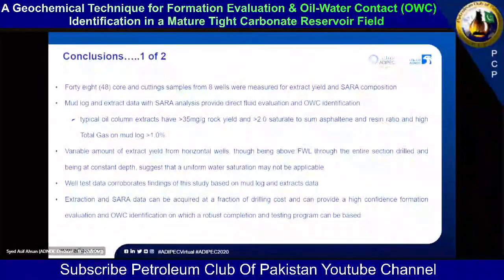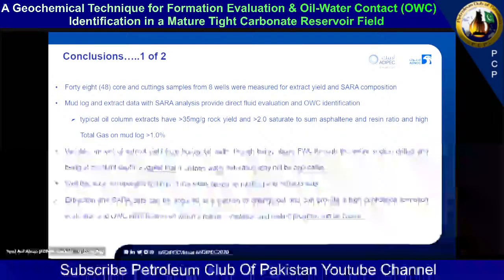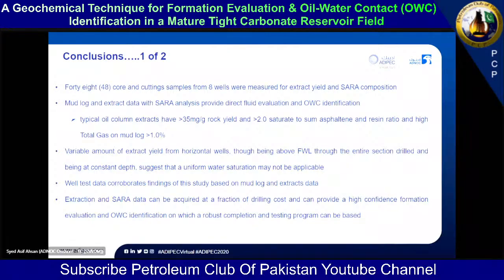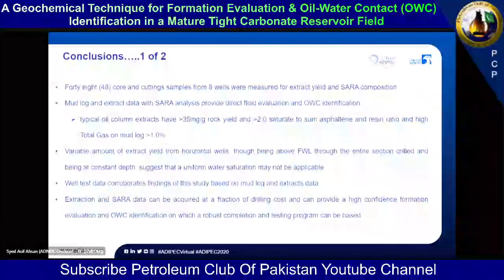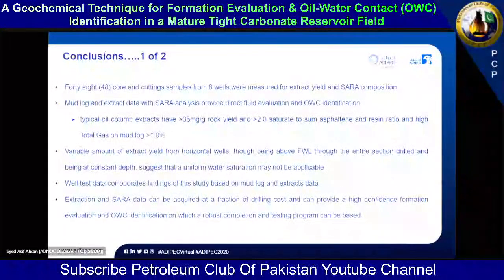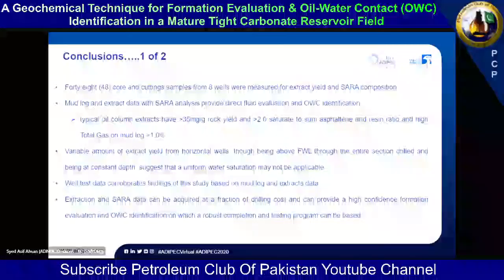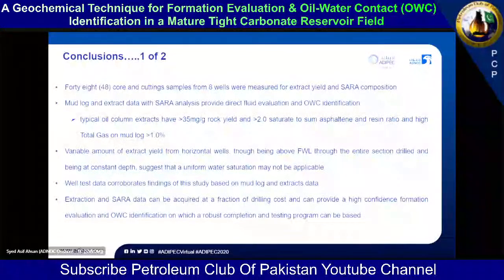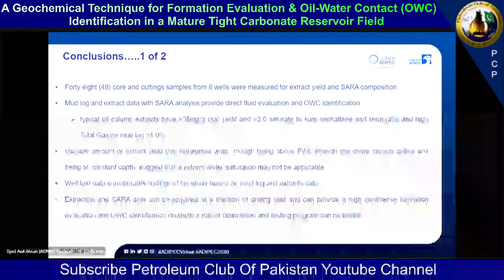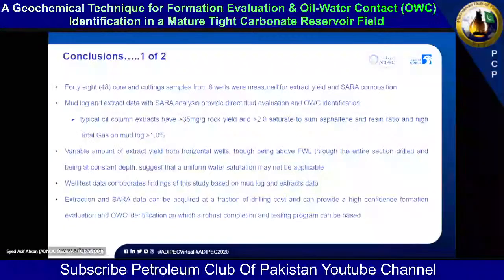In conclusion, 48 core and cuttings samples from 8 wells were measured for extract yield and SARA composition. Mud log and extract data with SARA analysis provide direct fluid evaluation and oil water contact identification. And you don't have to assume those mathematical expressions that we use for Archie and many other indirect methods of saturation assessment. Typical oil column extracts in this case have greater than 35 milligram per gram of rock yield, a saturate to resin ratio greater than 2 and as high as 14, and high total gas on mud log, typically above 1% total gas. And 1% is 10,000 ppm in the case of mud log.